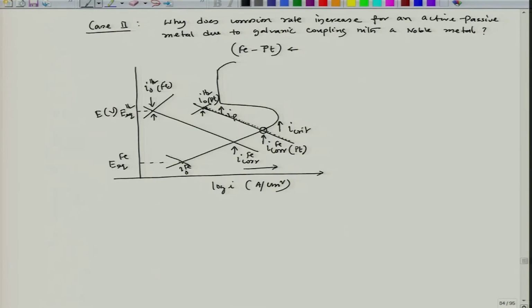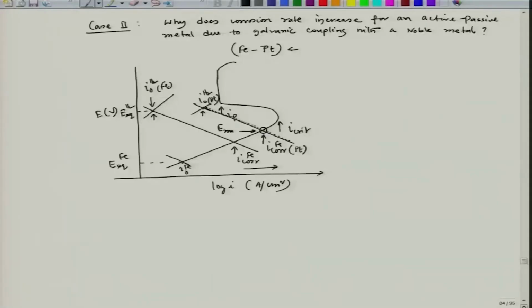So that means there could be two possibilities: if the mixed potential lies on the passive zone, I would be able to reduce the corrosion rate drastically. But if the E mix, this mixed potential, lies in the active zone, the corrosion rate would increase rather than decrease. So these are the two situations we have explained.